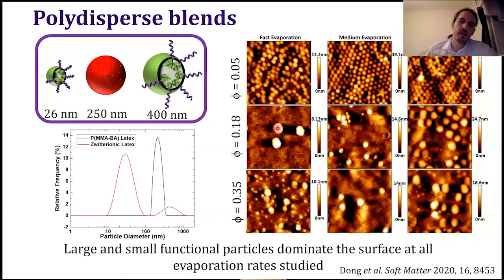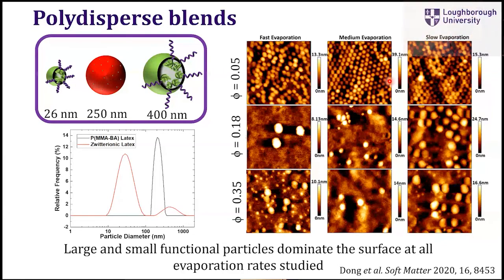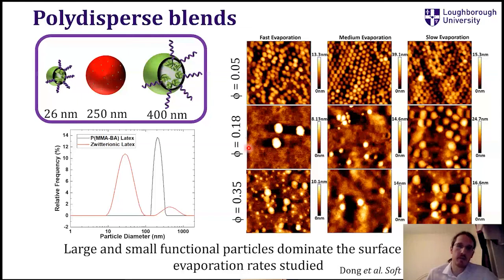you can see, and I can tell you by the sizes, that when you have enough of the functional particles, all you see at the top is just the functional particles. These are just the medium particles here, but all the rest, you have very small and very large particles. So the functional particles are always dominating at the top surface, which is what we wanted. And this is happening for a wide range of evaporation rates. It doesn't matter if you evaporate fast or slow, you always have your functional particles there. So this system seems to achieve what we want.